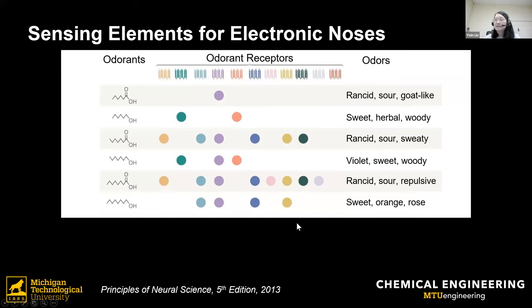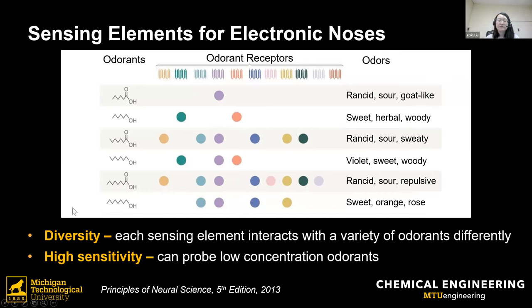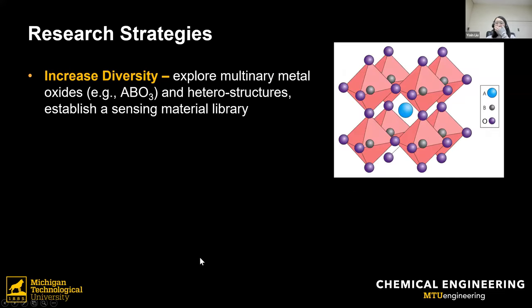So this is exactly the same scenario for metal oxides. The metal oxides can show response to several gases. And if we manipulate the metal oxide composition, they can have different sensing profiles, which have the same functionality as the odorant receptors. So we could leverage the diversity of metal oxides to create our electronic nose. And another important aspect is we wanted to enhance the sensitivity of the metal oxide so it could probe lower concentration odorants. So to do that, the research strategy we used in our lab,